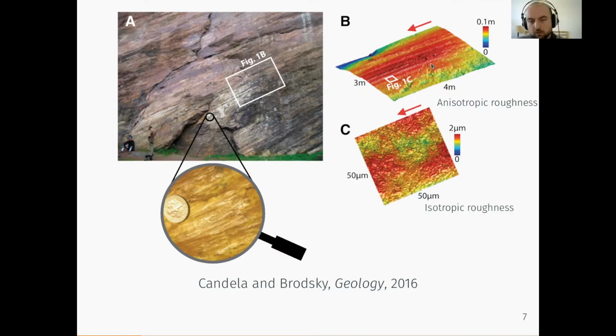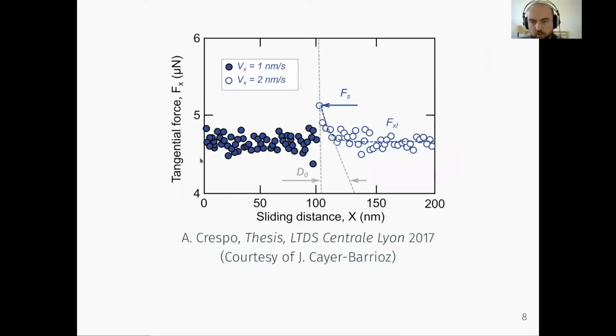There are also characteristic length scales for friction. These are some of the experimental results I will discuss a bit today from LTDS Central Lyon. I will discuss them further, but basically for now, what you need to know is that it's a sliding experiment where the velocity is adjusted during the sliding process. They measure the friction force, and when they change the velocity, they have an overshoot in the friction force, which decays towards a new steady state value. And this decay occurs over a characteristic scale d0.